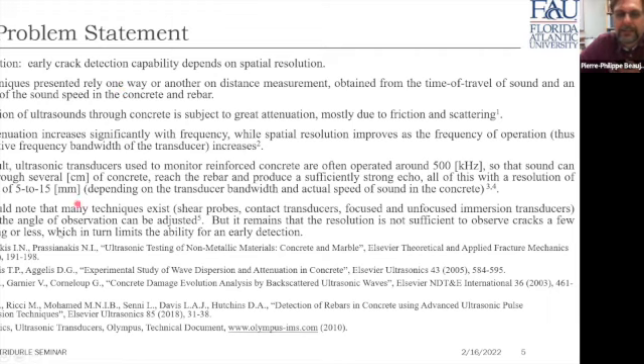mentioned in the previous slides and in this type of references over here, rely one way or another on distance measurement obtained from the time of travel of sound and an estimate of the sound speed in the concrete and rebar. Now, propagation of ultrasounds through concrete is subject to great attenuation, mostly due to friction and signal scattering. And such attenuation increases significantly with frequency, while spatial resolution improves as frequency of operation increases, thus increasing the effective bandwidth of the transducer. So there is an issue here.